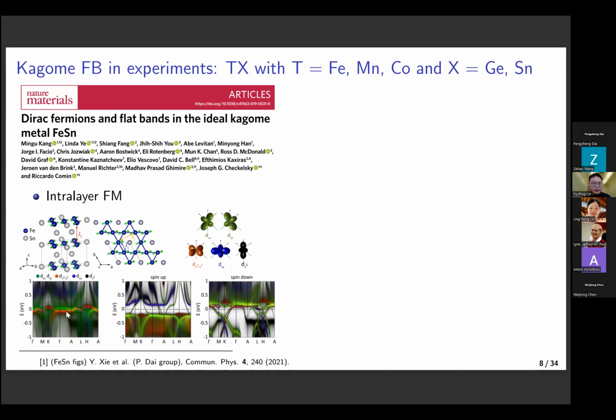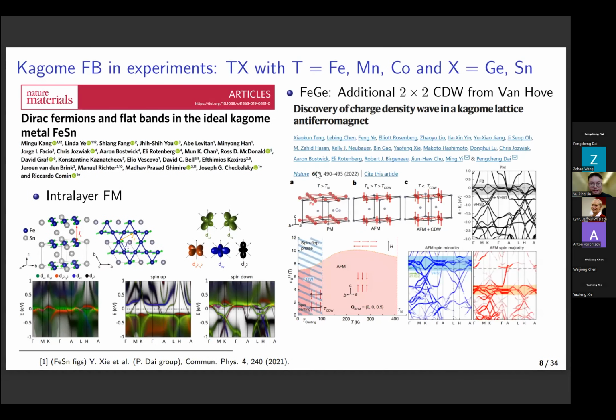And if we go below a certain temperature, for example around 400 Kelvin, it turns out that the kagome network forms intra-layer ferromagnetism, so that there is a Stoner splitting between the majority and minority spin bands. This is what is found in the iron tin material. More recently, it was discovered by the Rice experimental group, Pengcheng's group, that in iron germanium, in addition to the intra-layer ferromagnetism, there is an additional 2x2 charge density wave, which occurs below 100 Kelvin. The reason for this CDW transition is that when we have the Stoner splitting between the spin majority and minority bands, the spin minority band has the Fermi level roughly at the Van Hove singularity, so that the electron interaction can drive the charge density wave. So we can see that in the flat bands, we can have very interesting interacting phases.